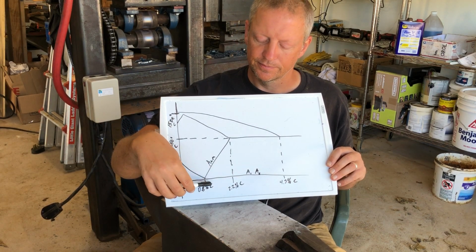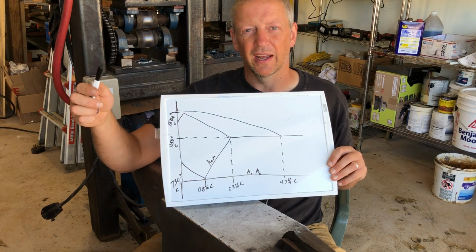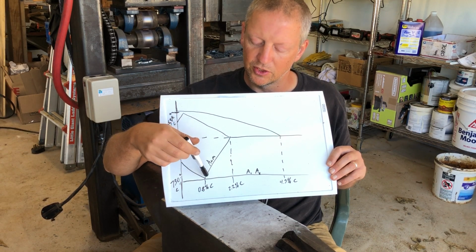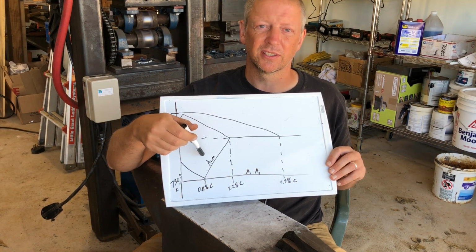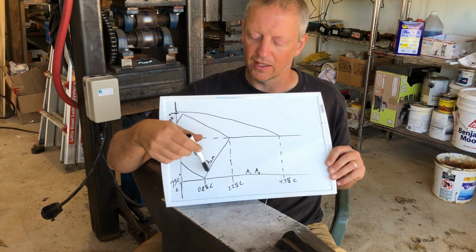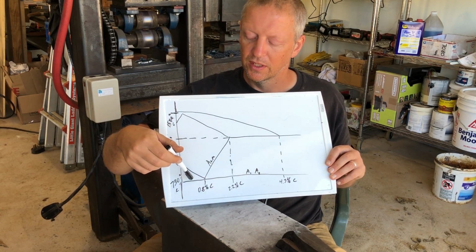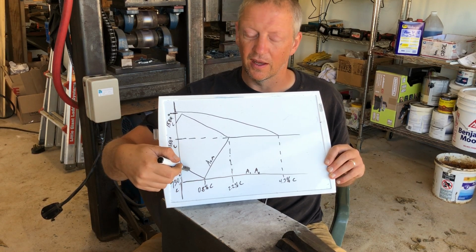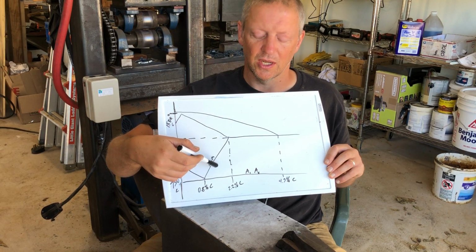And to one side, you've got excess carbide. To the other side, you've got excess pure iron. So the reason that you need a higher temperature to get into the pure austenite zone, to either side of that, is it takes a certain amount of time and temperature to dissolve on this side excess ferrite, and on this side excess cementite.